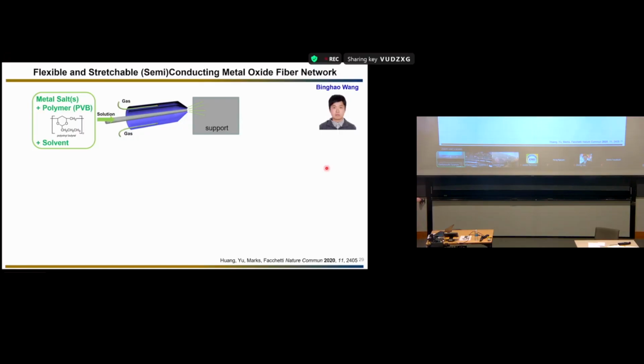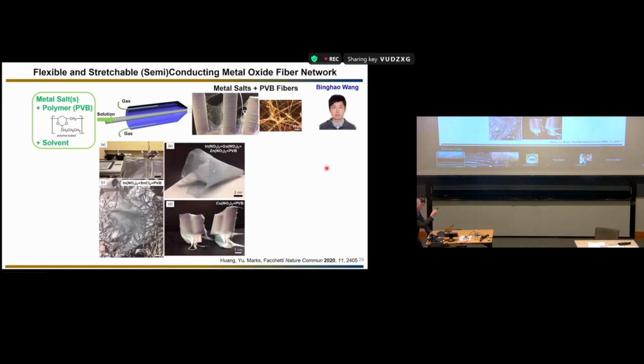Another way we did it is basically spraying. So we use a sort of polymer to somehow absorb your salt, your indium oxide precursor, for example. And what you do, you spray the formulation instead of spin coating the formulation. And what you end up with is you start getting fibers. And I think I have a picture, yes. So these are silicon wafers, and this is on purpose. I asked the student to take the silicon wafer, separate them, so you see. And you see that you get this fiber.